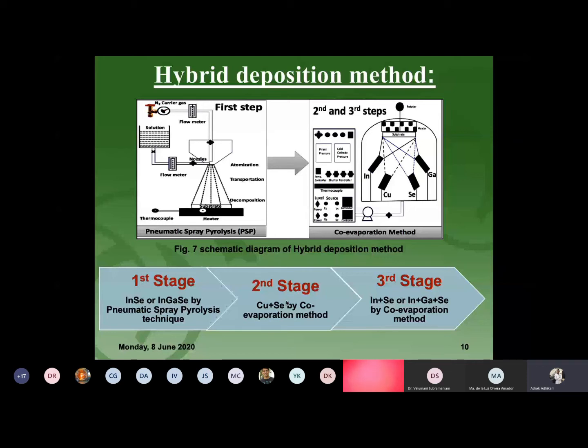The second and third stages of the hybrid method involve the co-evaporation method. In the second stage, copper and selenium were incorporated over the indium selenide or indium gallium selenide deposited in the first stage.